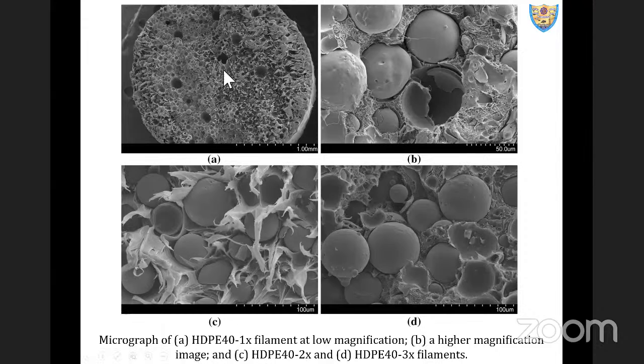Now this is the filament, and you can see small micro balloons here. If you follow the pointer, you can see here one, here second, third, fourth. There are many. In addition, you can see these void pockets. These are air pockets, and these are because of the machine limitation. As I mentioned, the machine we have, a single screw extruder, is a non-vented type, and thereby the flue gases get entrapped. Interesting to see is that these entrapped gases are uniformly distributed. We have reported that as well. Such voids are beneficial for damping applications, shock absorber applications, compressive applications, but definitely detrimental from the strength perspective. So based on the application, you can induce these or eliminate these.